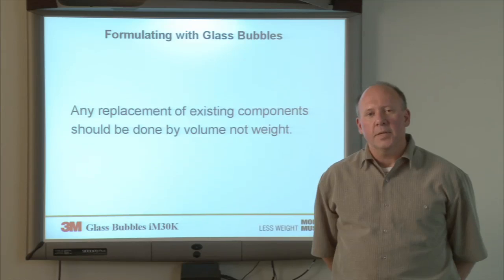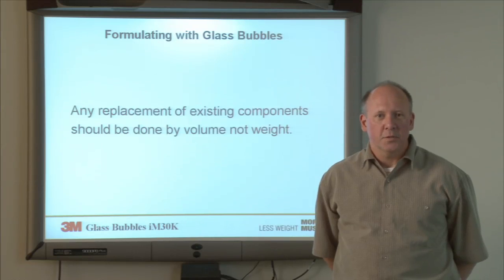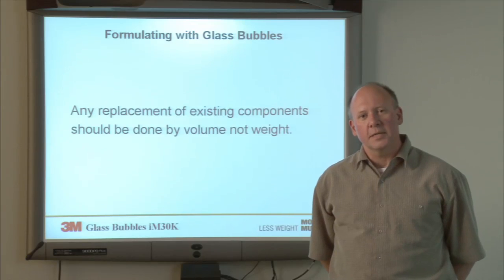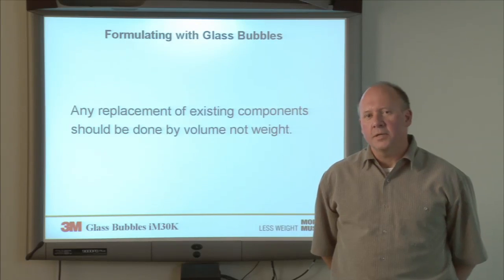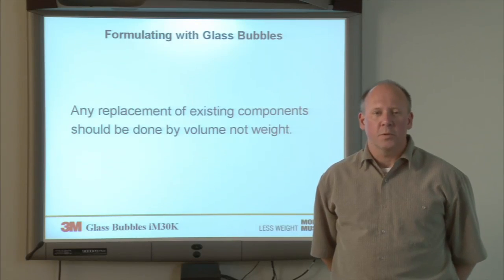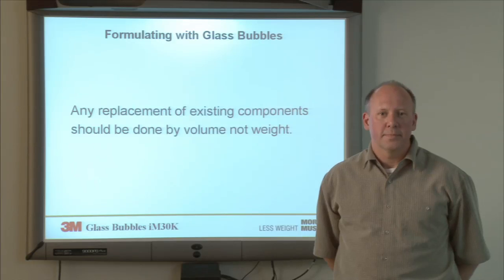Formulating with glass bubbles can be tricky. Glass bubbles are low in density, so they take up a lot of volume per unit of weight. So any replacement you do of fillers already existing in a composite material should be done on a volume basis when you're replacing them with glass bubbles.